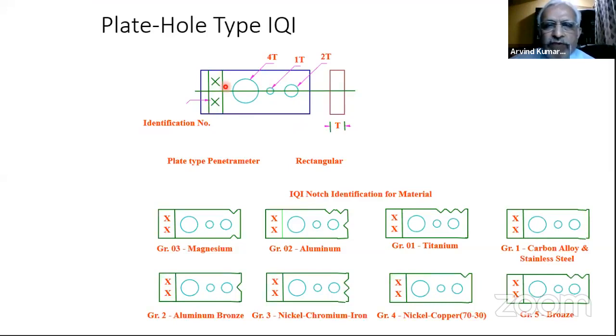So hole type, you have some thickness of the penetrameter based on the designation given here. It is almost 12 thou or 15 thou, that means 12 thousandths of an inch or 15 thousandths of an inch. That is the thickness of the penetrameter. And over that you have either 1T, that is 1 thickness diameter hole, 2 thickness diameter hole, and 4 thickness diameter hole. They're all arranged in this fashion only. The smallest hole is in between, then the next one is towards the end, and the bigger one is towards this end.